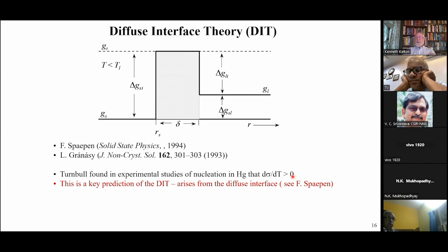Now, if you think about that, the interfacial free energy is a free energy. So it should have some delta H minus T delta S term. So it should have a negative temperature dependence, but it didn't. It had a positive temperature dependence. And this has been found over and over and over again in other liquids, as well as in silicate glass experiments. The diffuse interface theory gives an explanation for that, which turned out to be exactly the one that Turnbull argued sort of just by physical insight.